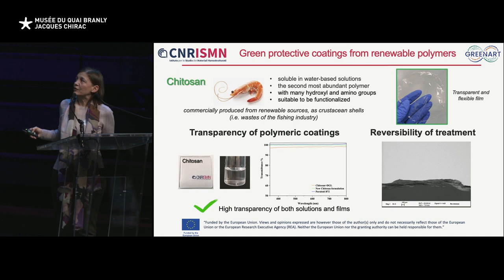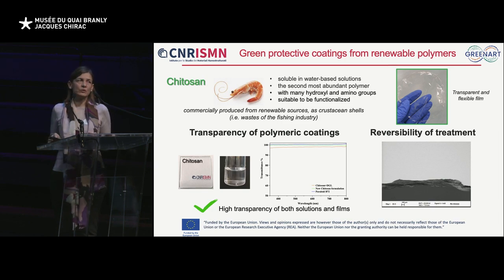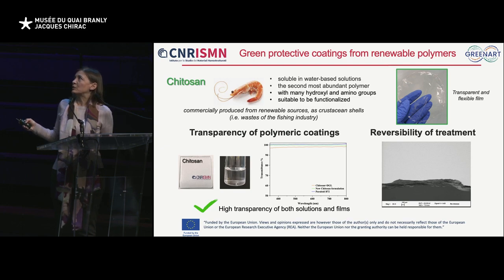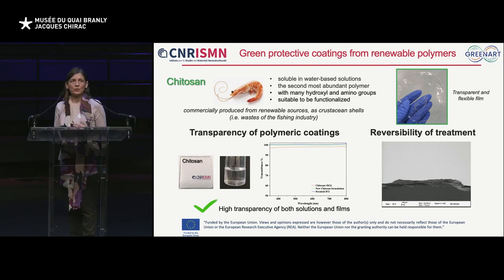And if we look, for example, in red, we can see the signal of the previous formulation, with green the new chitosan formulation developed in GREENART, which is quite close to the transmittance of Paraloid, which is a commercial acrylic resin. And we have also a very good reversibility of the treatment, which was proved by scanning electron microscopy.